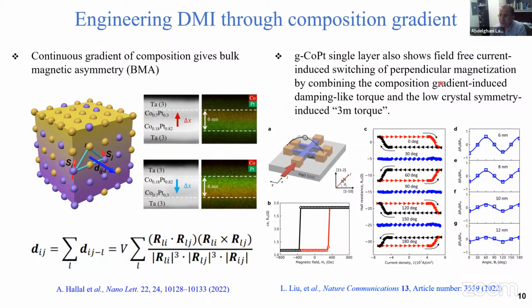shown that you can induce field-free switching. You can switch the perpendicular magnetization. This is believed to come from the composition gradient-induced damping-like torque and also low crystal symmetry induced 3m torque. So this paper described it very well. And there is also another system, cobalt terbium, where you can also induce switching due to DMI as well as bulk magnetic asymmetry. So that makes this system interesting not only for skyrmions but also for spintronics. One can combine these properties to study interesting physics phenomena and for different kinds of applications.